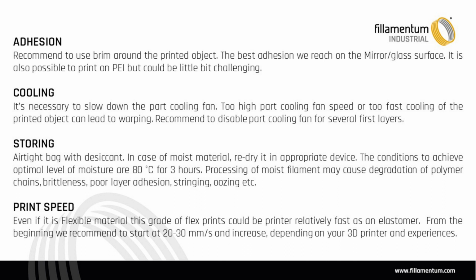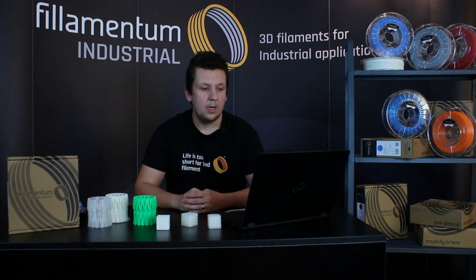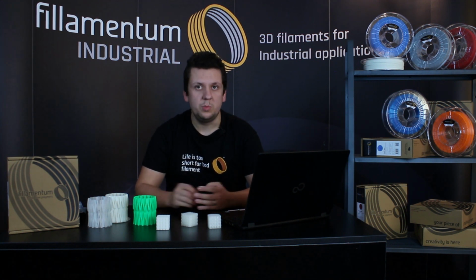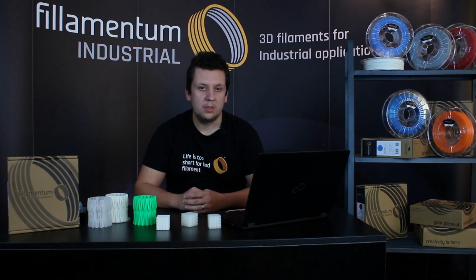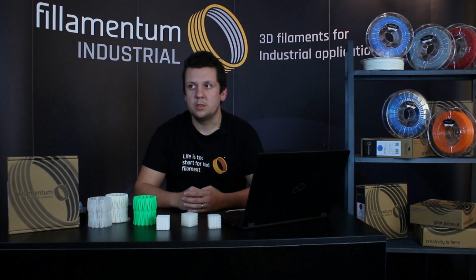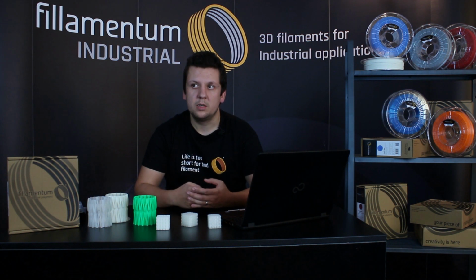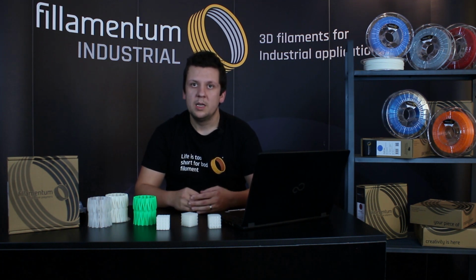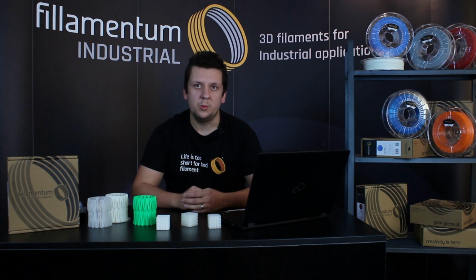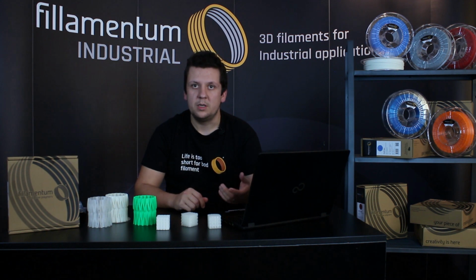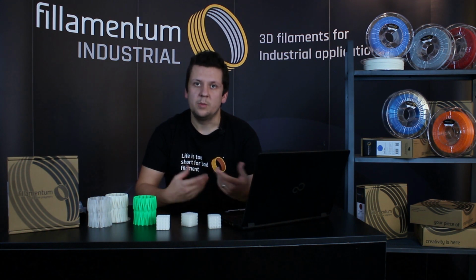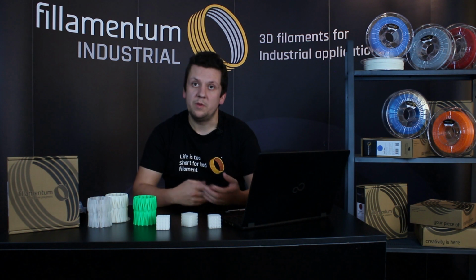If you have wet filament, you can redry it for 3 hours at 80 degrees Celsius, and it should be okay. But after redrying, it's good to let the filament cool down in a stable environment with stable humidity, because if you put the material on the printer hot and print, the material absorbs moisture again very quickly.